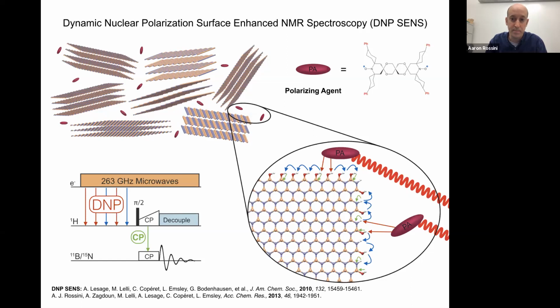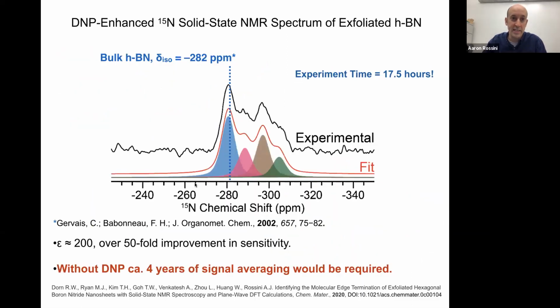So this is the DNP-enhanced nitrogen-15 solid-state NMR spectrum of the exfoliated hexagonal boron nitride. This is natural abundance nitrogen-15, so the DNP was really critical here. We had DNP enhancements of about 200 for this material with TEKPol, so that corresponds to over a 50-fold improvement in sensitivity. It took about 18 hours to acquire this spectrum, and so this is a nice example for Bob. I know he likes to put up examples like this. Without DNP, this would have taken about 4 years of signal averaging to acquire.